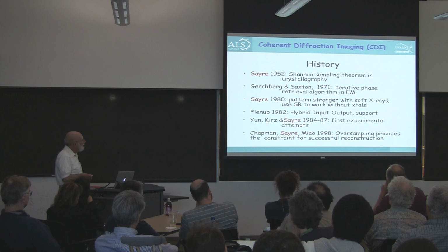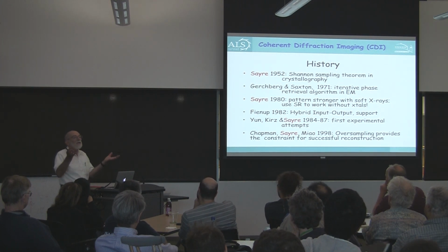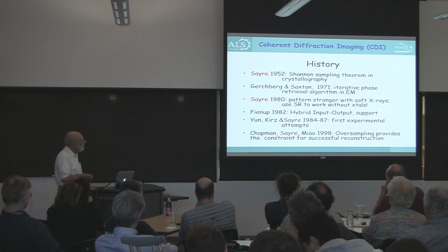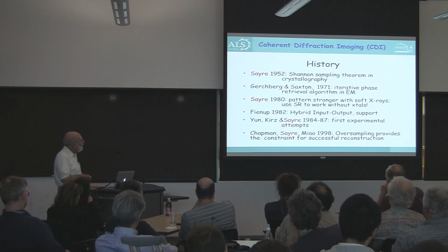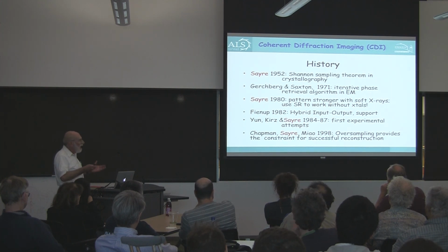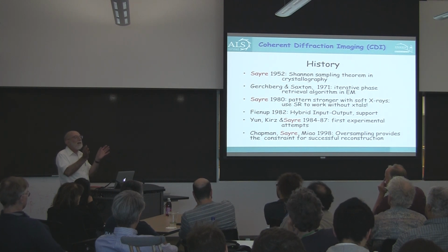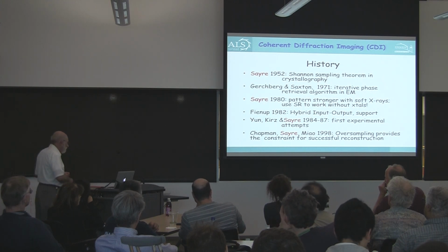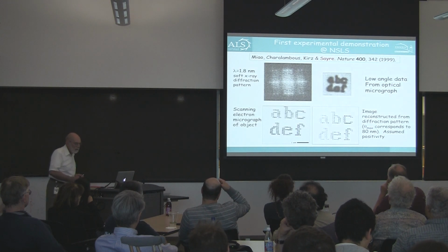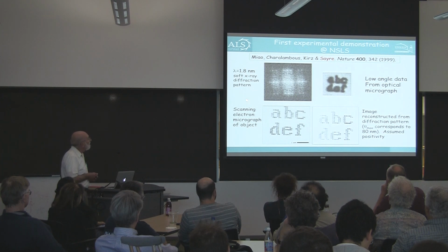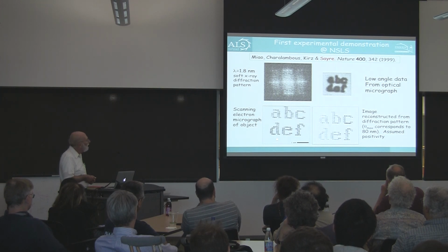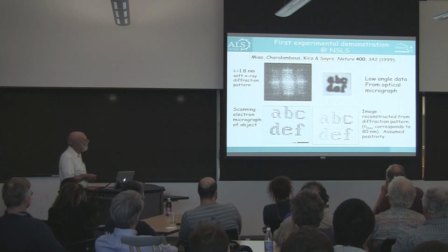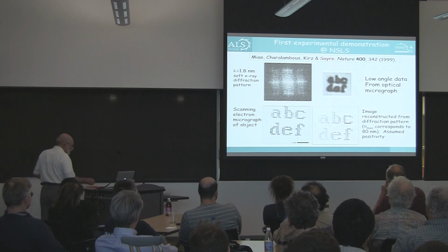In the meantime, David Sayre insisted that we try to find whether a non-crystalline object is going to give a diffraction pattern, which we were successful in doing in the 1980s. And then Henry Chapman, along with David Sayre and John Miao, who at that time was a graduate student, showed that, in fact, if you could record this diffraction pattern, then at least in the case of a model calculation, one could use the Fienup algorithm to create a successful reconstruction. And next year, experimental demonstration became available when we took an artificial object, a bunch of gold dots that were deposited on a silicon nitride membrane. This is the scale bar of 1 micron. This is the speckle pattern recorded, and a successful demonstration of the reconstruction was performed.